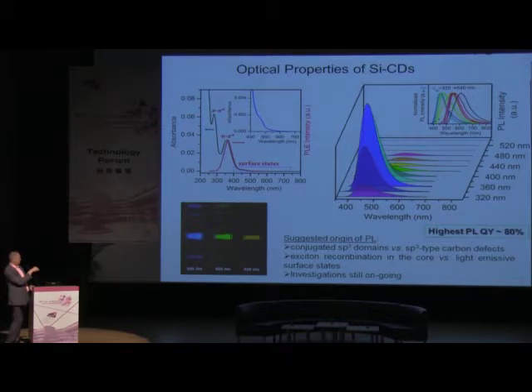What you can see from this photograph and also from this collection of photoluminescence spectra. So we take one and the same sample, we excite them at different wavelengths, and you can see that they can emit green light, blue light, also yellow light, one and the same sample. Their absorption spectra look like shown here.